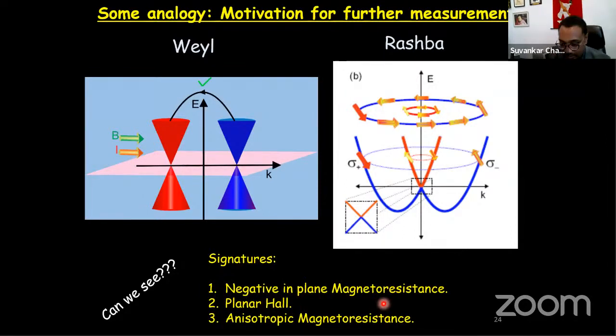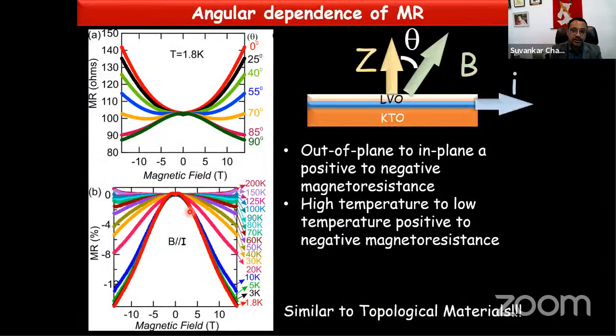So we asked the question, can we see this kind of thing in our material or not? So this is the transport geometry. You apply the current along the X direction, and the magnetic field making an angle theta with the Z direction. So we define our XY plane as the interface of this material, or the 2DEG of the material. And you can see when theta equals 0,